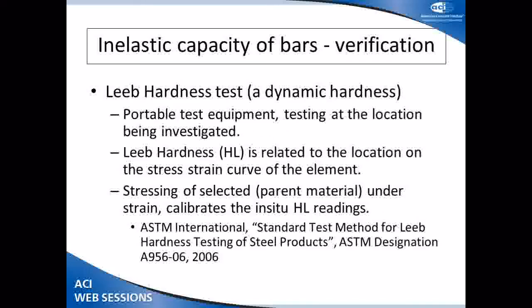The way we're doing this is with the Leeb hardness test. It's a dynamic test, it's portable, it's a little device, it's calibrated. We calibrate it against the stress strain curves of the parent materials. We take bars from different parts of the structures where the bars have not been highly stressed. And this is based on an ASTM standard. And we can relate those Leeb hardness tests to where the bar is on that curve. And that makes it so we can then judge how much deformation capacity that building or that element has remaining.